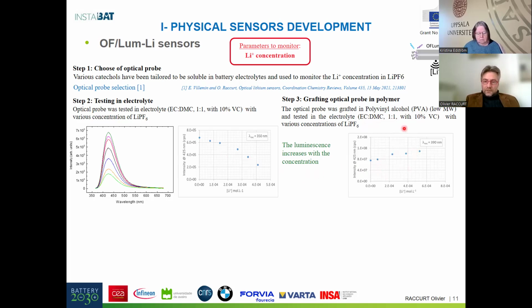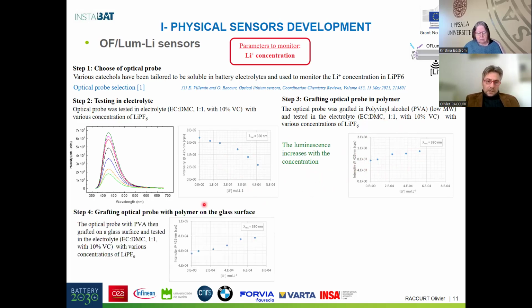It's an inverse behavior, but it's due to the interaction between the PVA and the molecule related to the luminescence. But the conclusion is it works, because we can monitor the concentration by the variation of the luminescence signal. And then to validate that, we grafted the molecule, the probe, onto glass surfaces.